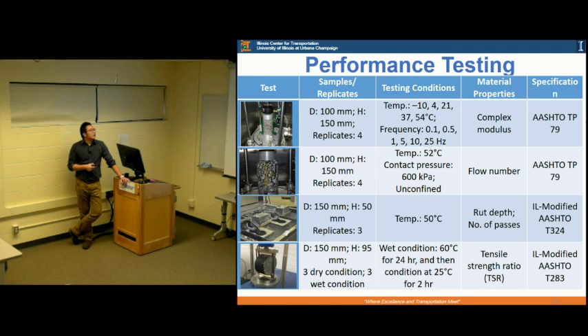So we run a lot of testing. Of course, we have a lot of equipment. For example, this is an E-star to measure the stiffness at different temperatures and different frequencies. And also we have the flow number - this is a rutting test. And also we have a Hamburg wheel tracking, at 50 degrees, to measure the rutting resistance. And also we have that moisture resistance test, the TSR, tensile strength ratio.